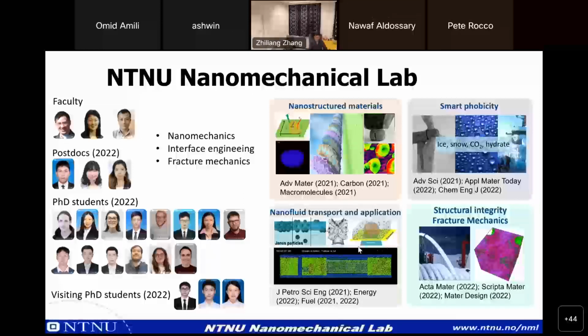The nanoparticles, for example, Janus nanoparticles, that means particles have 2 phases, were diffused to the triple junction between oil, water, and solid, and to enhance the disjoining pressure. So we have been carrying out quite a lot of simulations to understand how the nanoparticles can influence the flow, disjoining pressure, and adhesion, wettability, etc.